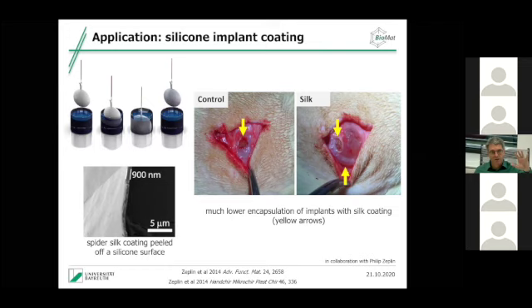So what happens is the cells go to the surface, and they would like to destroy this foreign material, but silicone is pretty strong, so it's not biodegradable. And what the cells then do, they start to encapsulate it. So actually, they start to make cartilage surrounding this implant, and they start to make a capsule. For the rats, that's not a big issue. For human beings, that can be an issue, especially if you're a breast cancer patient, because you have a depressed immune response system. And therefore, these capsules can really cause severe side effects.